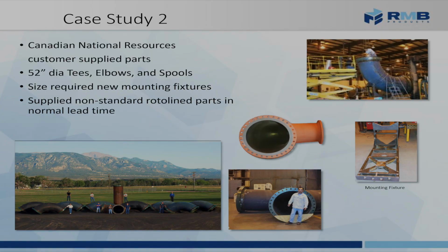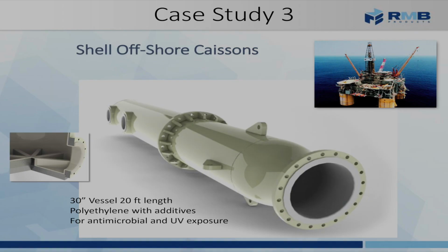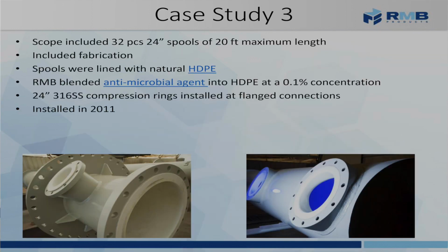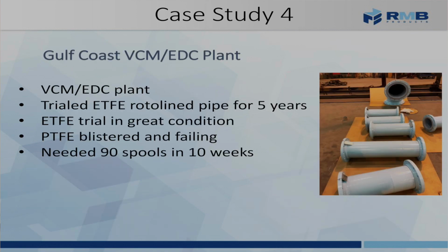Another example, this is for CNRL, supplied these 52-inch diameter elbows. And at first, we did not even know if these were going to be something we could do because they were so large. And we came up with a mounting fixture to be able to rotoline them. And we're able to take that project on. So that was an oil and gas application. Also, quite a bit of work goes into offshore platforms using the BioArmor, which is the HDPE with anti-mic. And in this case, this was these caissons, as well as quite a bit of HDPE line piping with an exterior top coat.